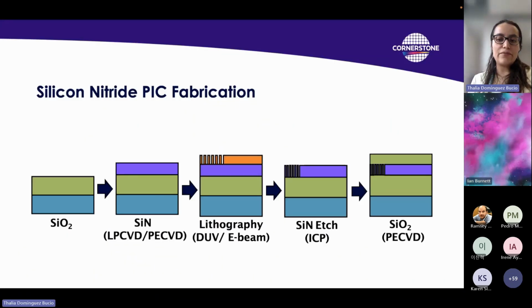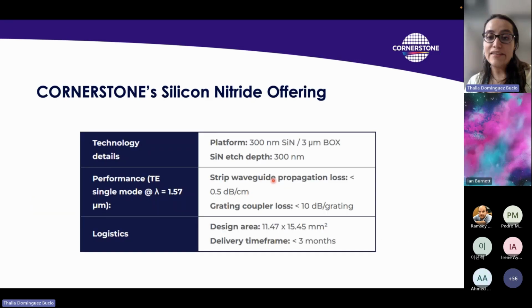Typically, the standard silicon nitride fabrication process is very straightforward. We start with a silicon dioxide layer, then we deposit our silicon nitride with either technique. We do the lithography, we etch the waveguides, and then we cap it. Or sometimes we will even open the cladding in order to get some sensing possibilities. Under this context, Cornerstone itself offers the standard silicon nitride platform, which is 300 nanometers of silicon nitride, and it's fully etched. With this material, we're getting losses around 0.5 dB per centimeter, and we have grating couplers with less than 10 dB loss per grating.